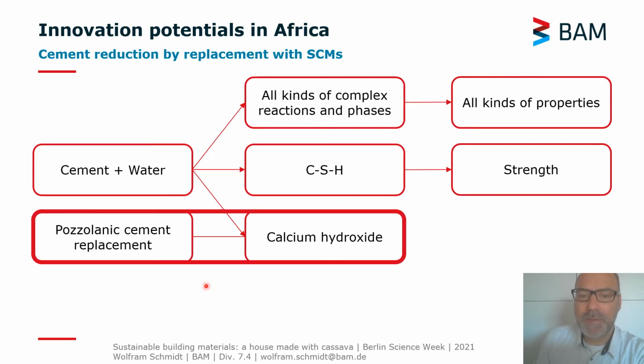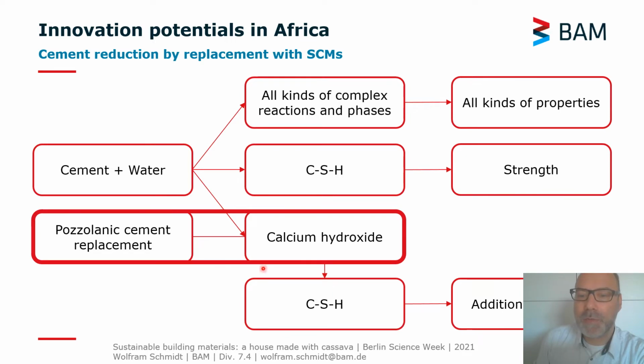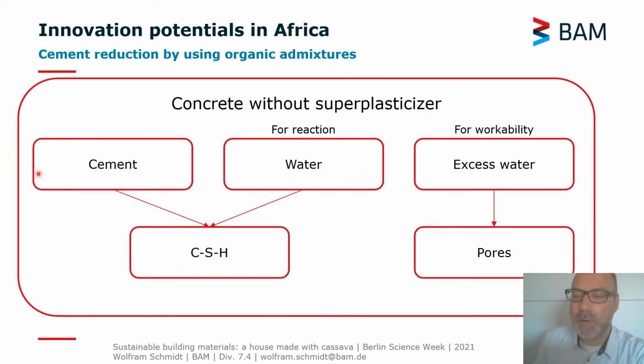And this reaction forms supplementary calcium silicate hydrates, which give additional strength to concrete. And this additional strength potential can help us to reduce the overall cement, or the Portland cement clinker, that we're using in our binder.